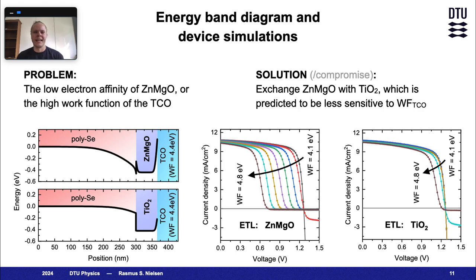To better understand the origin of the transport issue, we carried out photoemission spectroscopy measurements to construct the energy band diagram. As a result of the very low electron affinity of zinc magnesium oxide, a very large transport barrier is formed at the heterointerface to the transparent conductive oxide. The severity of this barrier is a function of both the work function of the transparent conductor as well as the doping density in zinc magnesium oxide, which is very tricky to get high.